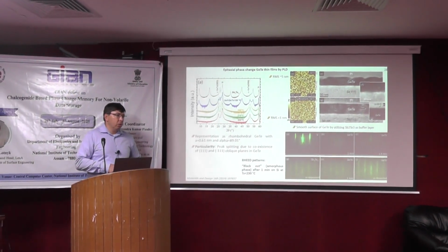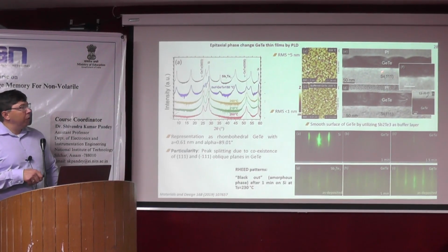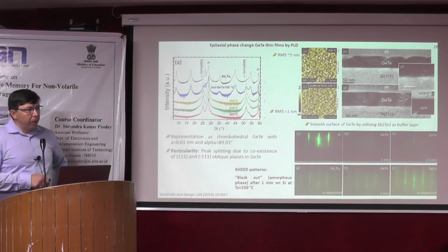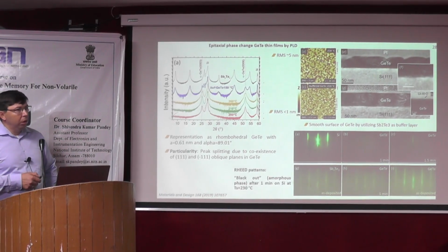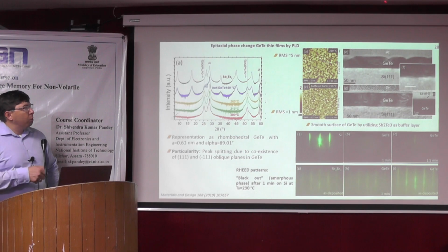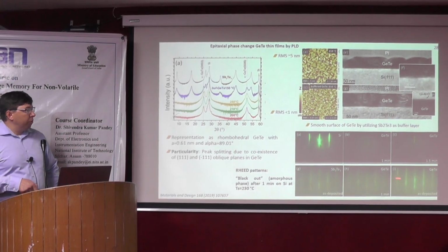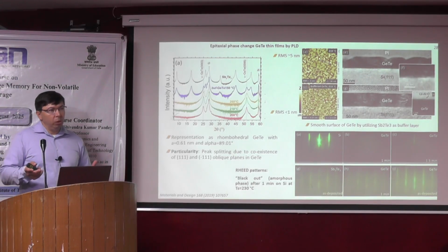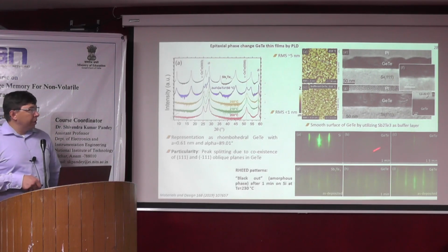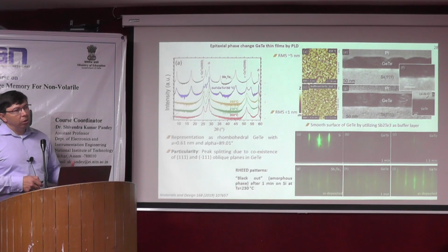Yeah, I think the formation mechanism here could be that antimony telluride and germanium telluride have some similarities in the crystal structure, so it can nucleate much faster, as in the case of silicon. Here you have a misfit of about 10%, so you have to overcome that somehow to form this structure. Because of the similarity, I think also the bonding of antimony telluride and germanium telluride is metavalent bonding. This phase can nucleate much faster on this surface.